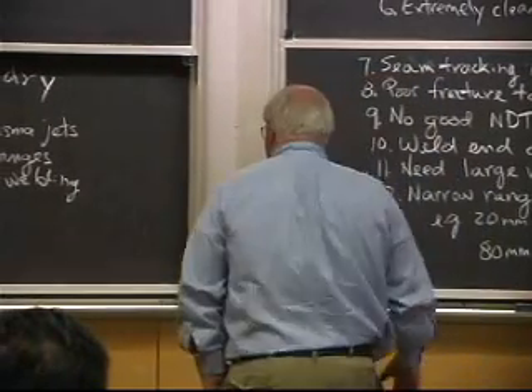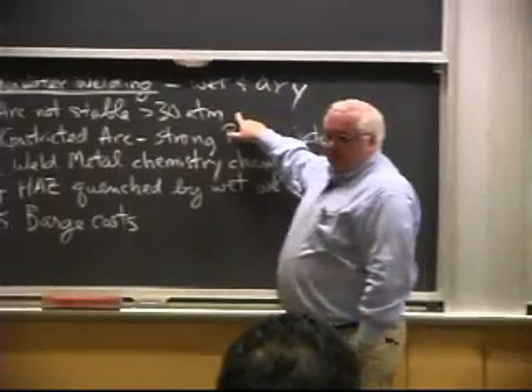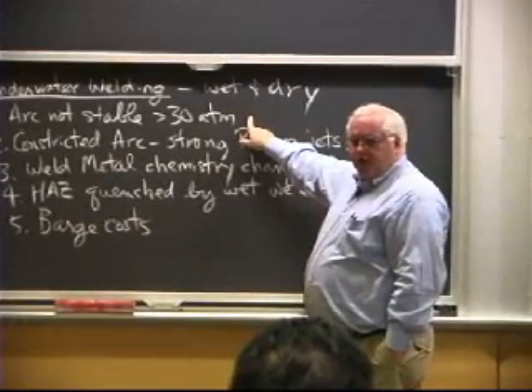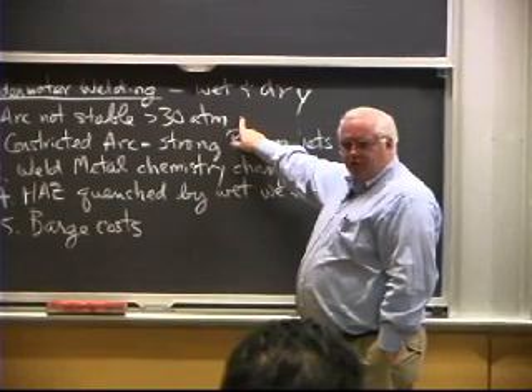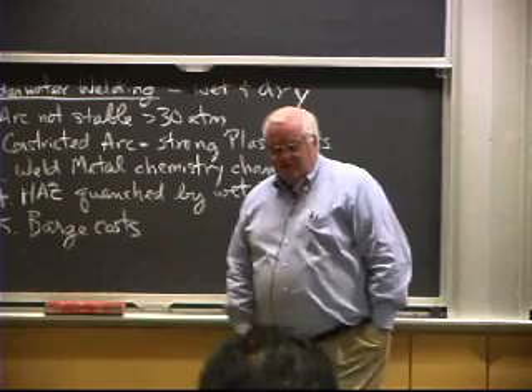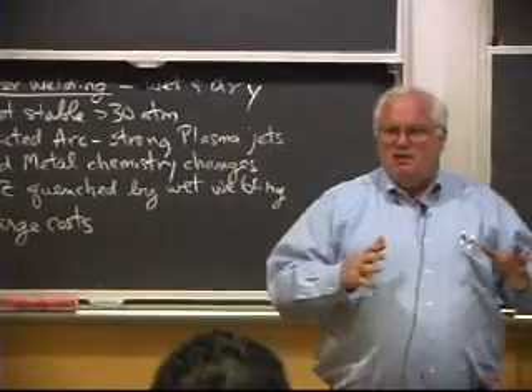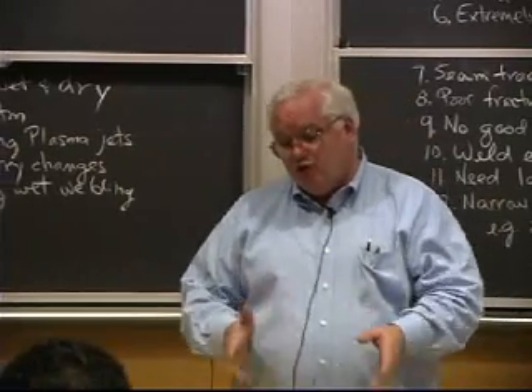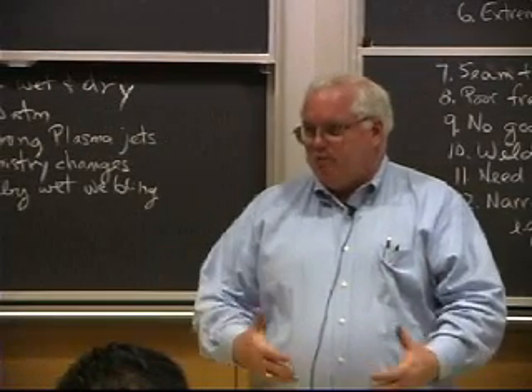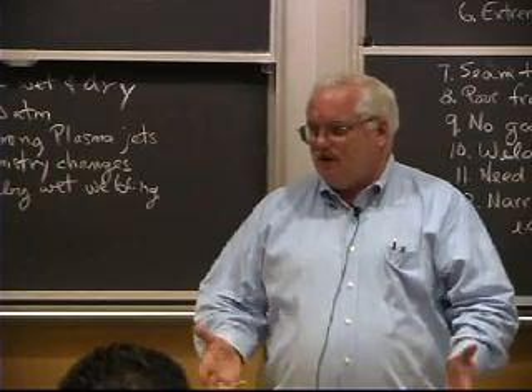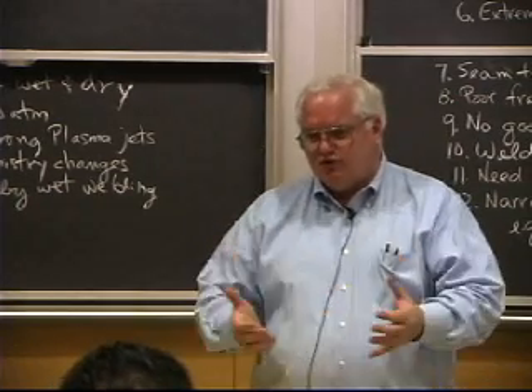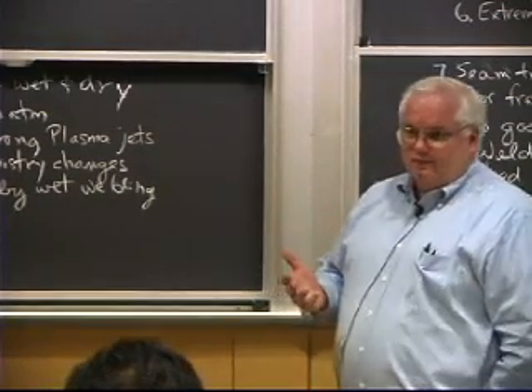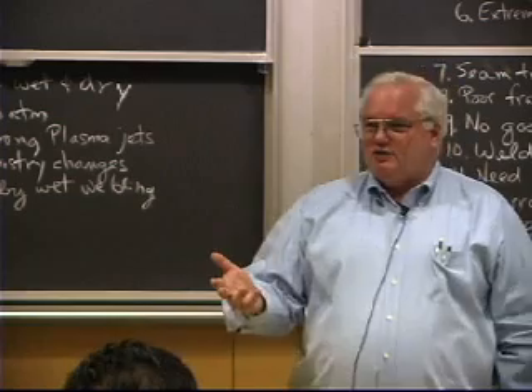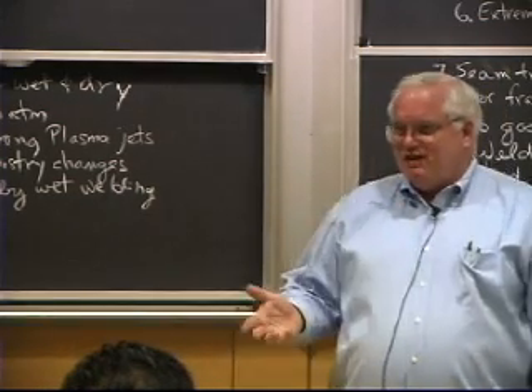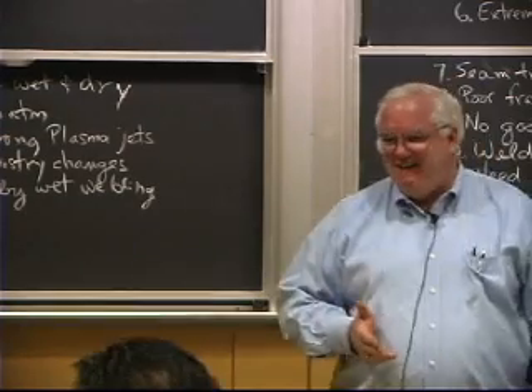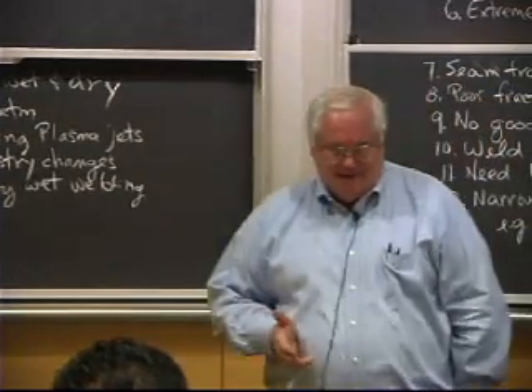Now, if you actually take 30 atmospheres, that says you can only go down to about 1,000 feet, because it's 440 psi and it's 0.44 pounds per foot, that's the reason I took 440, right? I divide, and I get 1,000 feet. Well, whether I'm doing it wet or dry, if I wanted to weld at more than 1,000 feet, you can do it, but you have to take a chamber with you and pump out the chamber to a lower pressure. You can't do it at the barometric pressure down there. Okay, so you have to build a chamber around it. If you're going to build a chamber, you might as well do it dry, because there's other problems with doing it wet. Now, I know you guys are interested in underwater welding, not at 1,000 feet, but about 30 feet, right? Or something like that. Okay? How to repair that ship when you get a hole in it, for whatever reason, right?